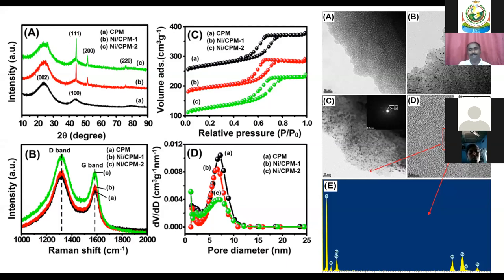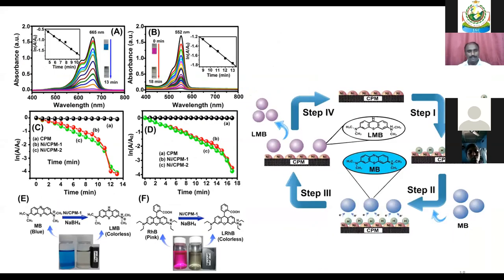And this composite is used for the dye reduction process. Methylene blue and rhodamine B are reduced using this catalyst. This is the mechanism of how the degradation process occurs during this catalysis. This is the catalyst, and in the first step, sodium borohydride enters the reaction mixture. It donates hydrogen, as borohydride BH4.